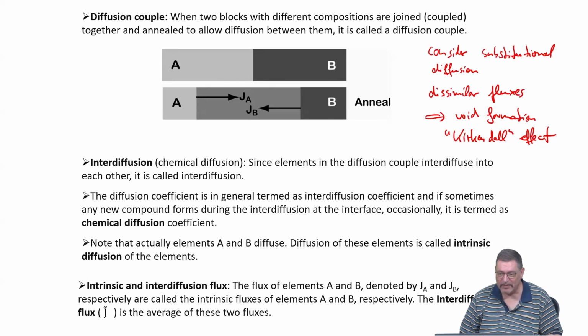I know it's many terms, and it's often due to historic development that people have been using them. I don't think it's very consistent, but that's the way it is. So the interdiffusion flux is just the average of the two intrinsic diffusion fluxes.